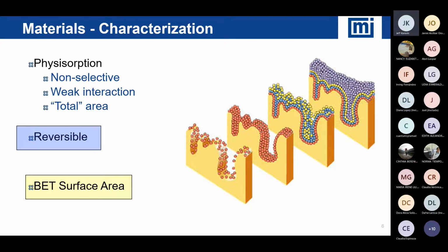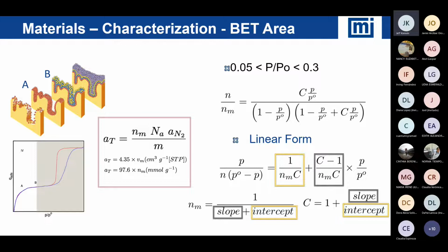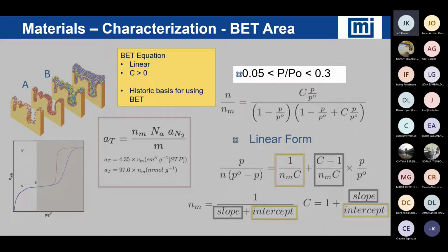And for many years, there were very simple rules about using BET surface area. One of them was how we look at applying BET surface area and actually reporting it and calculating it. So it was a very narrow range. Universally, we would consider that when we measure adsorption, we would look at relative pressure ranges from about 0.05 to 0.3.